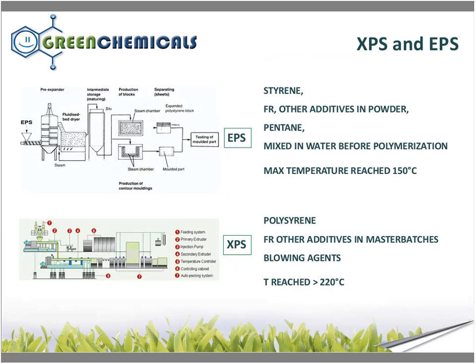So, we first studied the solution. We made some lab tests and we obtained the formulation. We now had to pass to industrial scale production. Just to let you understand, I would like you to point attention to these two technologies. In EPS, you work with the styrene and you have to make a polymerization. And in this technology, you put additives in powder form. On the other side, when you work with polystyrene, you obtain XPS and the additives are put in master batch form. In this technology, the temperature that we reach is above 220 degrees. So we needed to create a master batch.